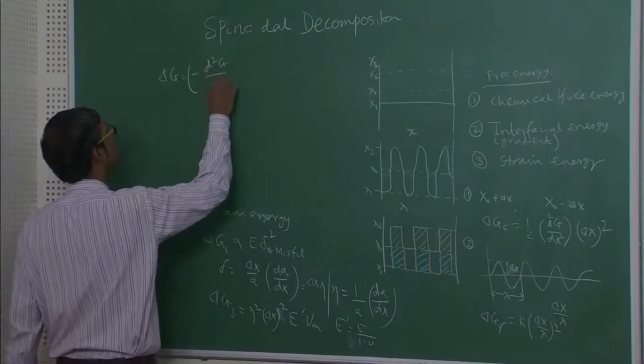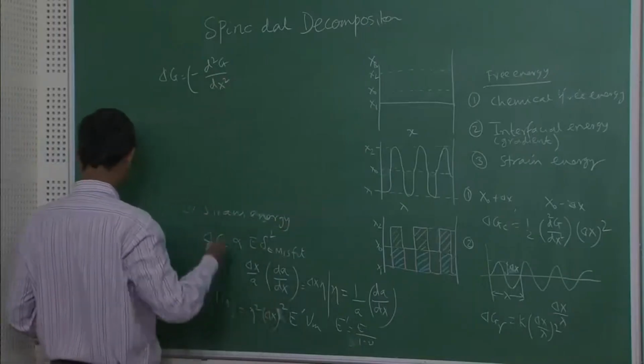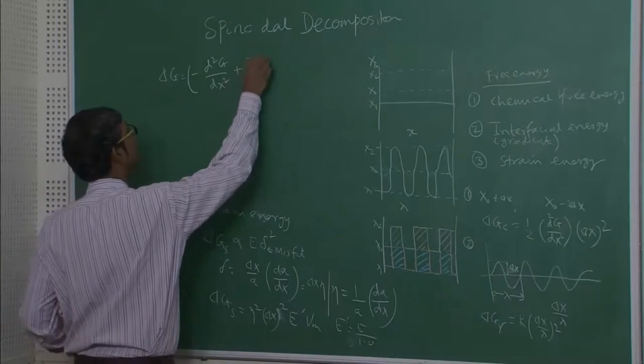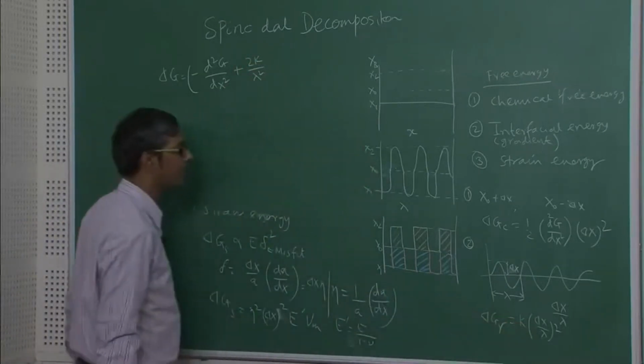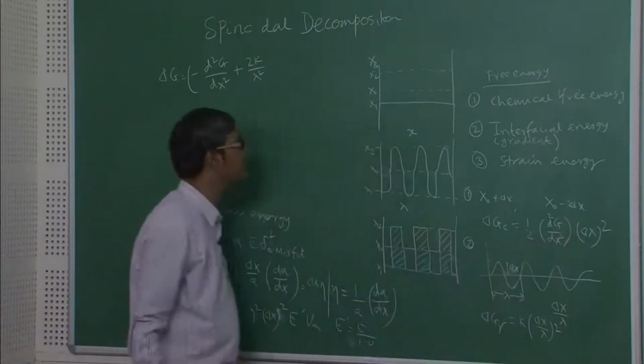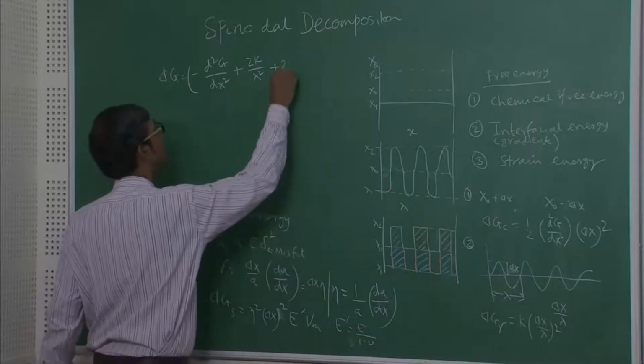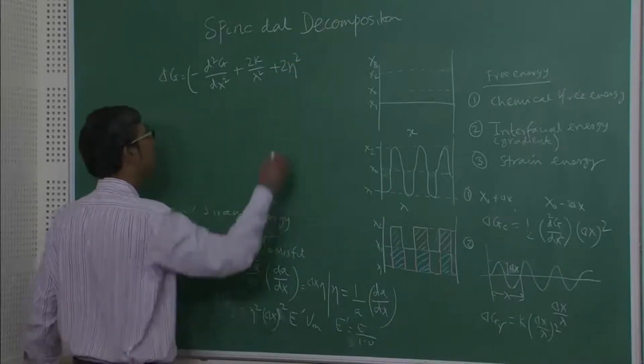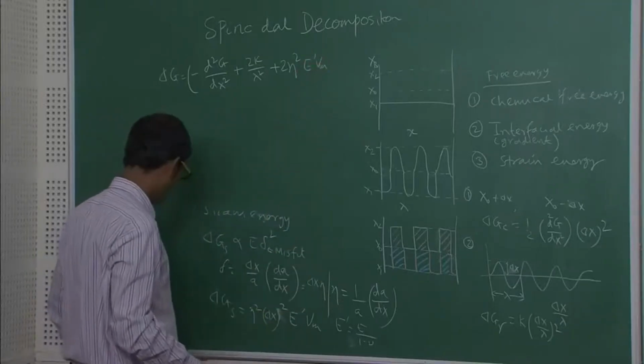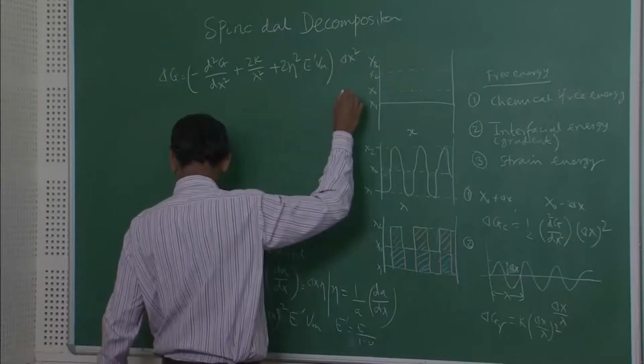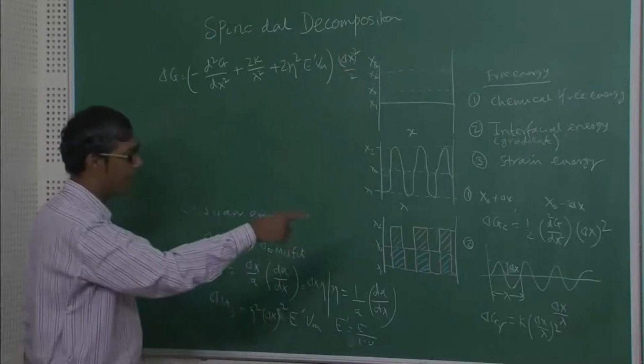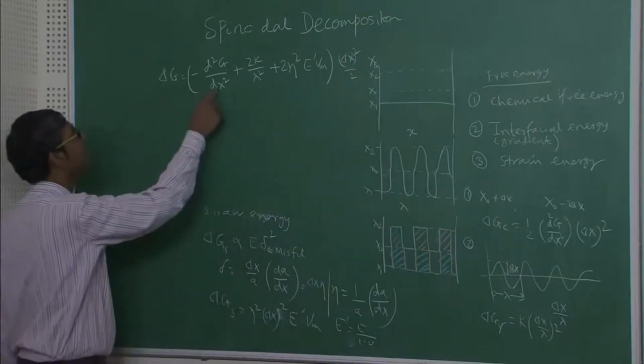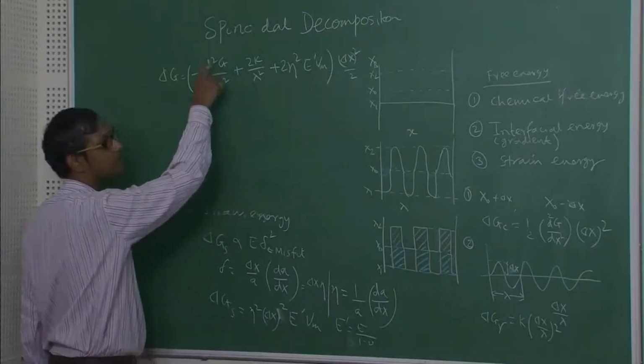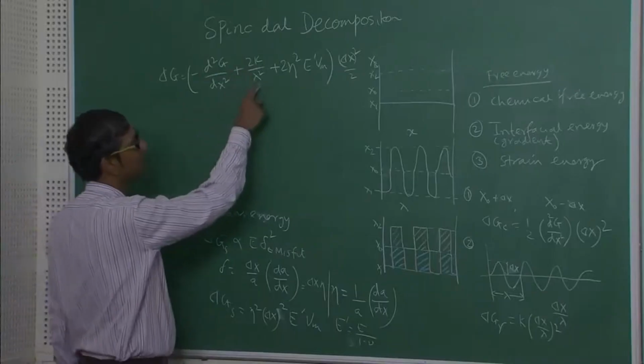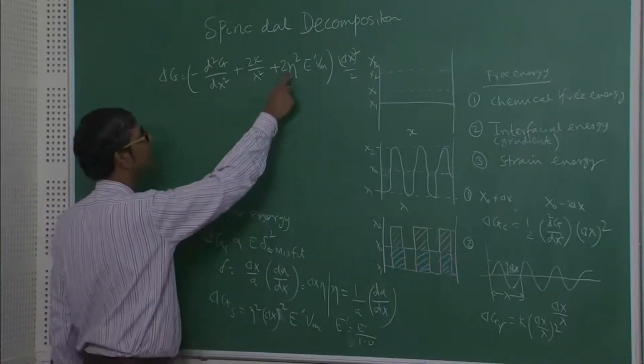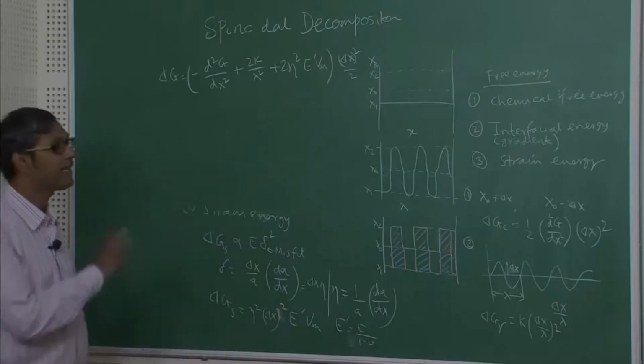So therefore I can write down these like this: minus this one, that term, plus 2k by lambda square, remember 2k by lambda square. Remember what we are doing, we are taking delta x square out from the system, basically, plus twice eta square E prime Vm into delta x square by 2, that half which is present here I have taken out. So that means delta Gc is basically half of delta x square into this term, and then the gamma is k by lambda square delta x square, and Gs is basically eta square E Vm delta x square. So we get the whole expression of the free energy.